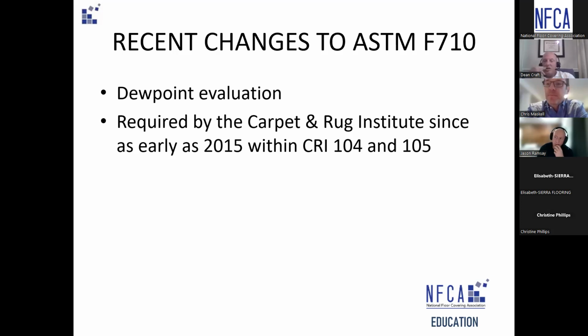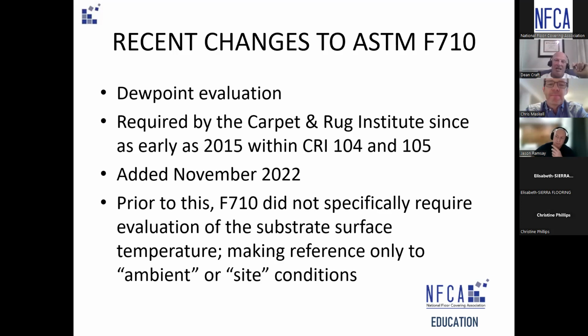Or like Jason mentioned, say your slab is a little cooler. Say your slab is at 65. And by the way, you can look at the dew point chart, that 65 to 85 box for temperature and that 35 to 55% RH. There are points on that where you hit dew point. So you could be at 55 RH and like 67 degrees, and you could be at dew point. You're in the box, but you're still at dew point. And think how insidious this could be. You could be at dew point spreading a water-based adhesive on top of a thin layer of moisture that you can't even see. That ain't going to work.